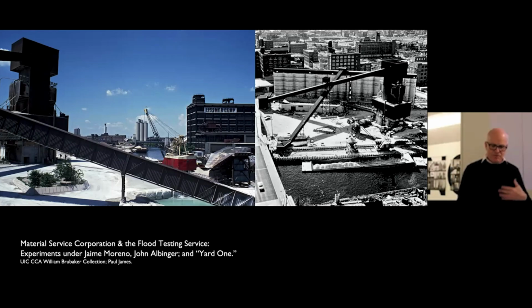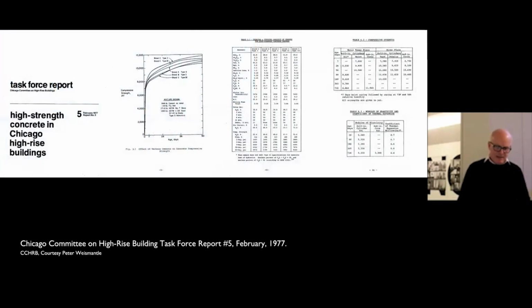And in addition to supplying material to the job sites, Moreno and Albinger are part of this group called the Chicago Committee on High-Rise Building that is looking at all aspects of skyscraper construction throughout the 60s and 70s. In 1977, there is a task force report that Moreno is one of the co-authors for, and they basically published dozens and dozens of pages that show that by tweaking the size of the aggregate, the type of the aggregate, by adding fly ash, by adding silica fume, and by experimenting with those proportions, you can get exponentially greater strength, even beyond what Abrams thought possible.